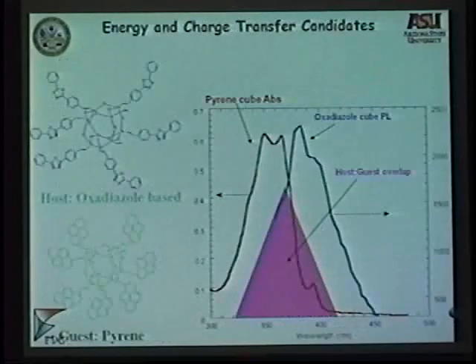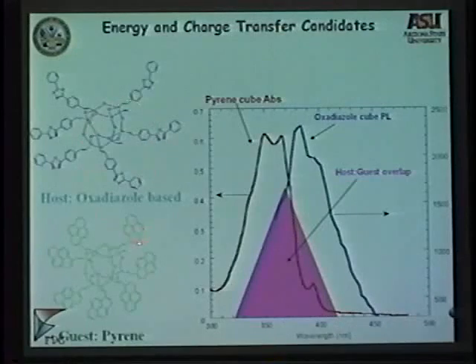And then the neat thing about these is you could have one single molecule or nanoblock basically, and you could modify the chemistry here and include one molecule that absorbs the energy from the surrounding molecules on the cube and emits its own light. So this is a demonstration where you have an oxadiazole nanocube and a pyrene nanocube, right? You mix them together and take first the absorption and the emission. You could see that the absorption of the pyrene overlaps with the emission of the oxadiazole. So anytime this overlap occurs, you're going to have Förster energy transfer very efficiently. And that transfer will allow the energy to be dumped from this molecule on this cube to this cube here, and this would emit its own light.